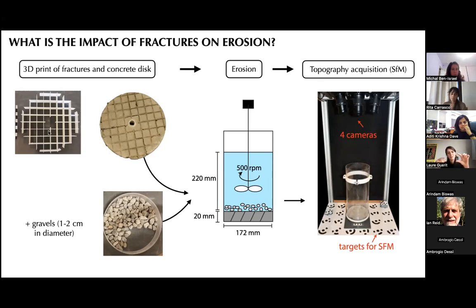And I did not show it, but once one block is gone, it is easier to remove a block just nearby. So we do observe spatial trends in plucking. One block is removed, and then you have a block just next to it, next with respect to the rotation of the propeller, of course. And we do observe this chain event of plucking. So I think this is why plucking is so efficient and leads to very high erosion rates. So the problem is that diamond shapes are more difficult to build in the lab.